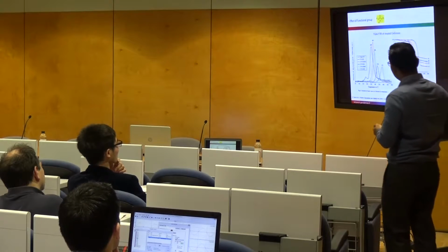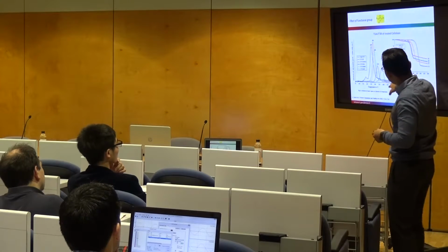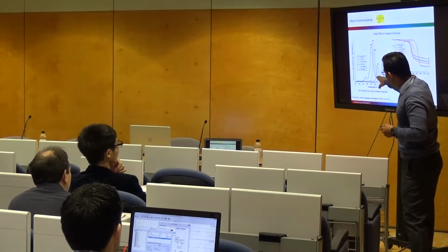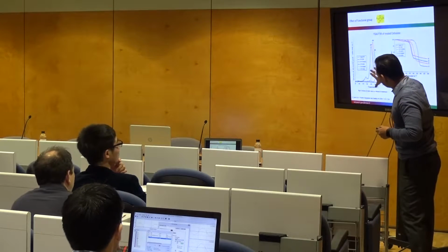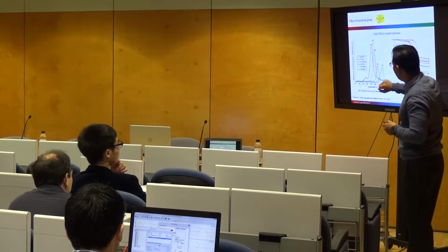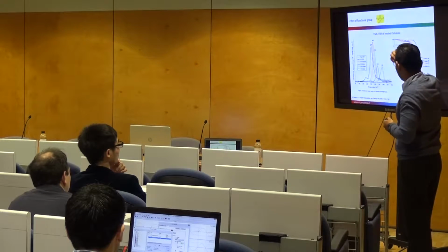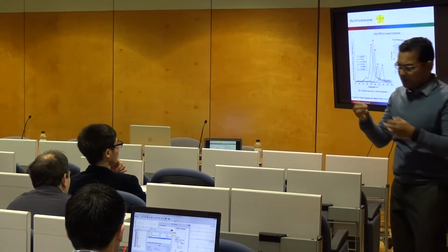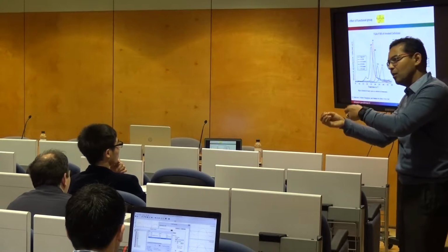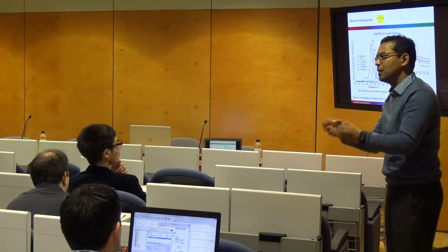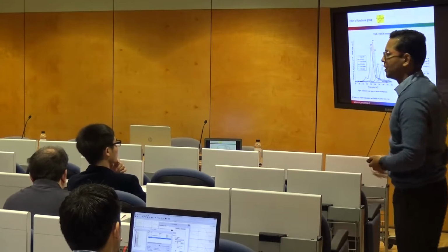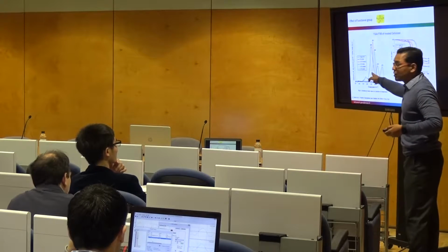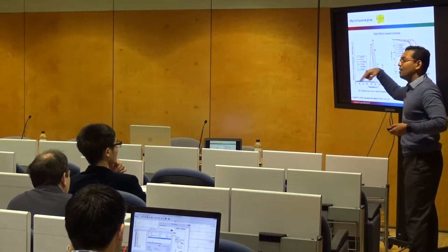For example, if you look at these peaks here, this is the amount of water being formed when you have a flame retardant there. When you have a phosphorus flame retardant in cellulose, the flame retardant reacts with cellulose, dehydrates the material, and releases a lot of water. What we are trying to do is measure the amount of water being released through FTIR data.